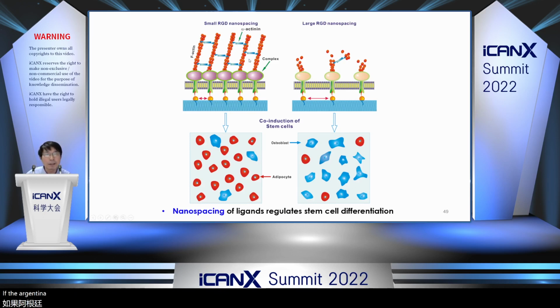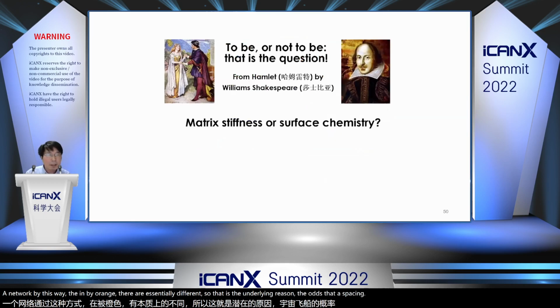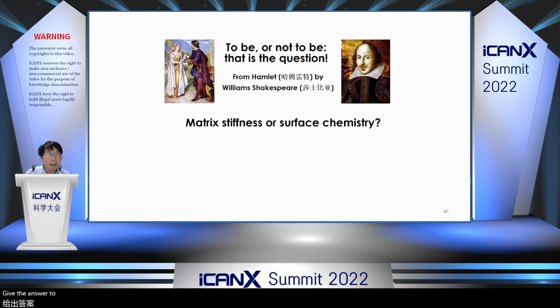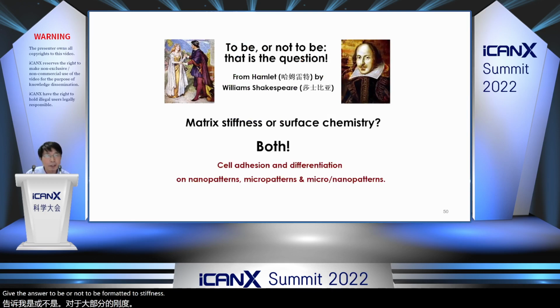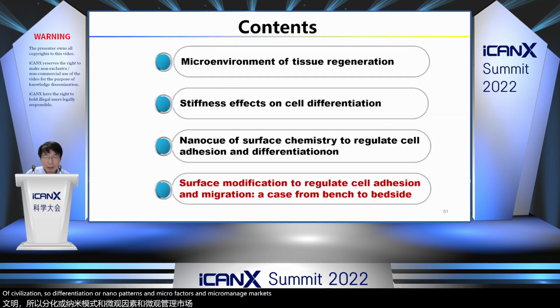If the RGD nanospacing is larger than the critical one, for instance, 70 nanometers, the lateral cross-linking by alpha-actinin could not work. So the cytoskeleton cannot form a network. By this way, in biology, they are essentially different. So that is the underlying reason, the RGD nanospacing. Now here we can give the answer to be or not to be. For matrix stiffness or surface chemistry, our answer is both. And also based on our careful examination of cell adhesion and cell differentiation on nano patterns, micro patterns and micro-nano patterns, we have reported a lot of pure fundamental research.